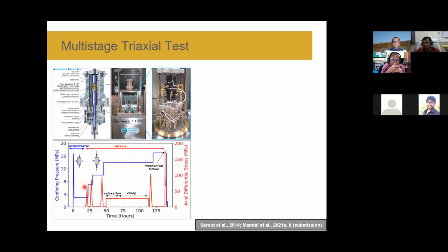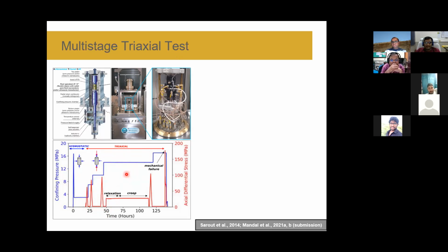loading rate itself. And at one of these stages, which we call the in situ stress condition stage, which we recreated, creep was measured. We apply constant axial stress at a given confining stress, and we leave the rock to deform within 6 hours. So this data was measured over 6 hours for all the samples, and that data was utilized to infer the creep deformation.